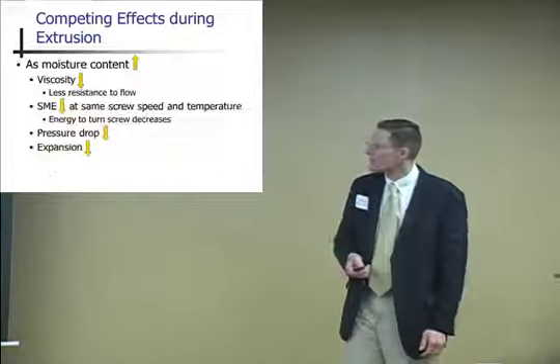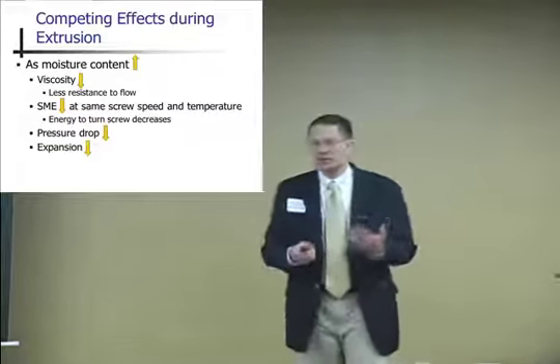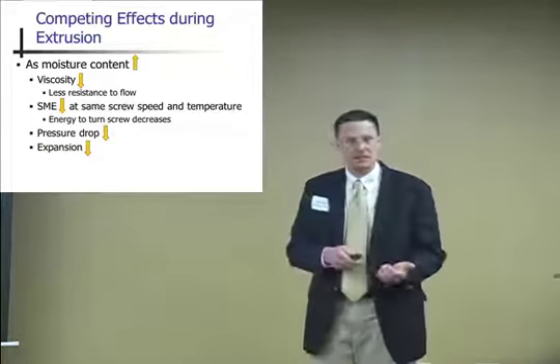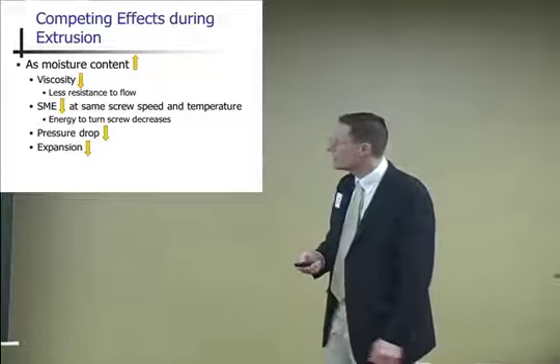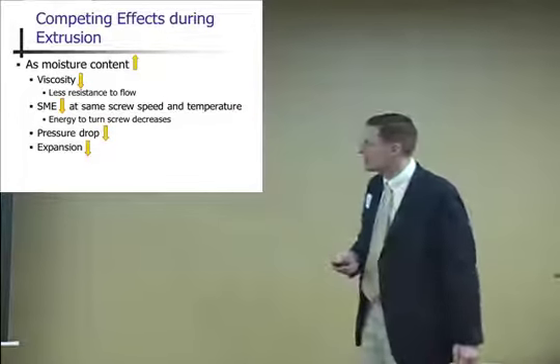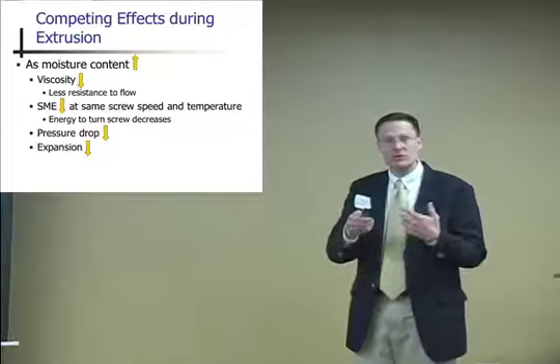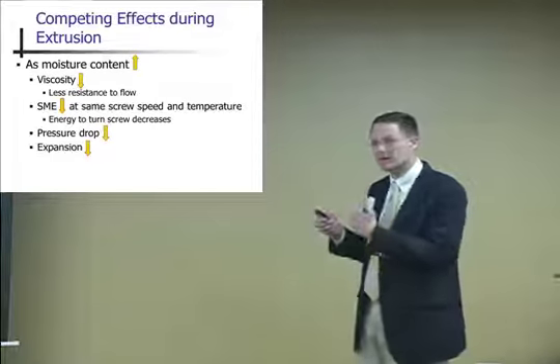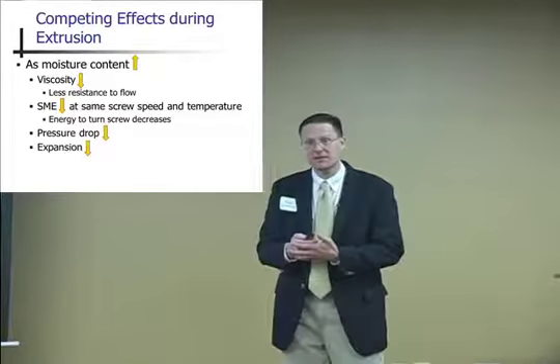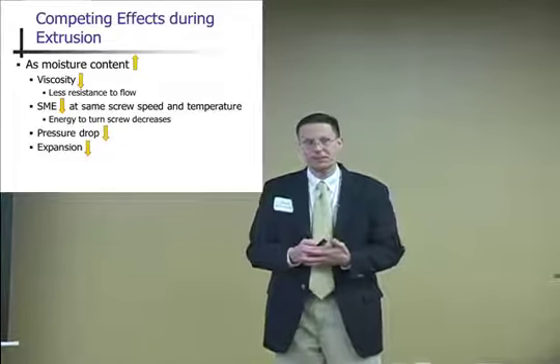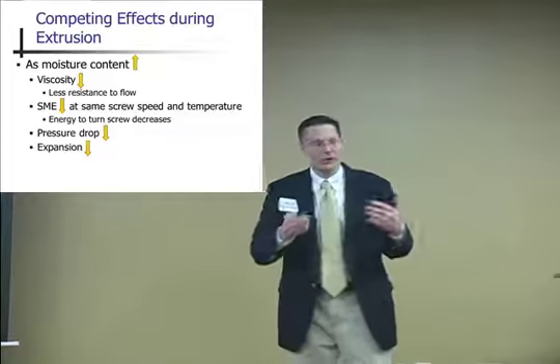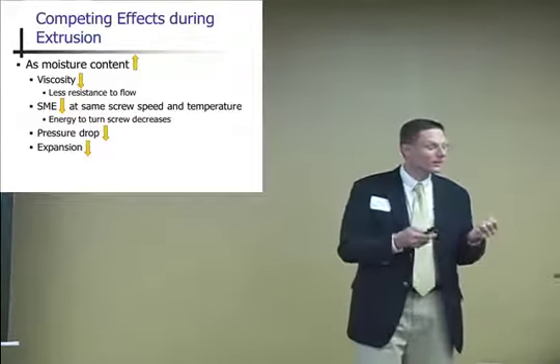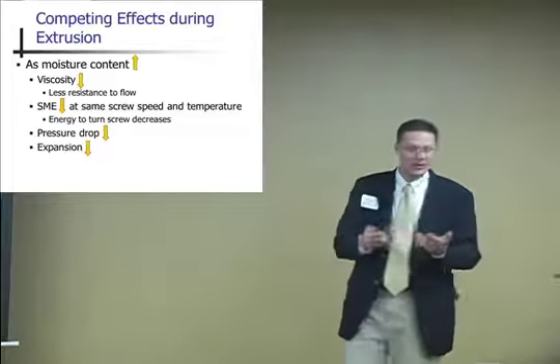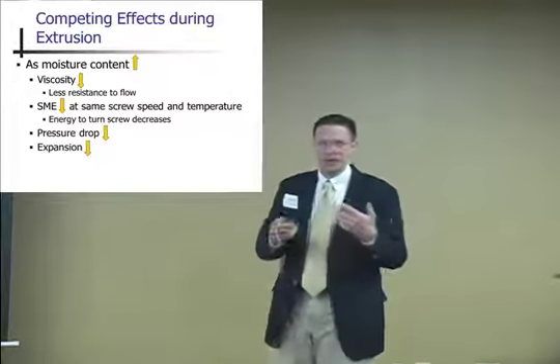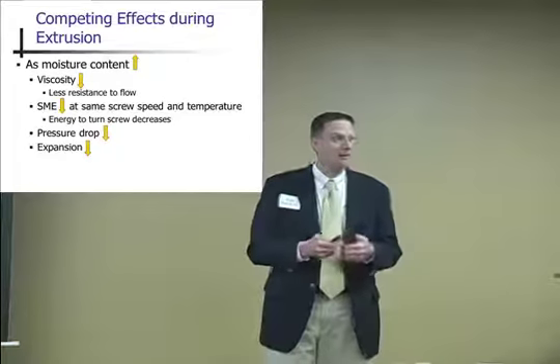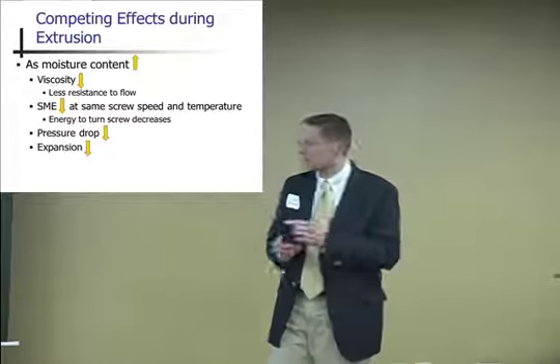Keeping everything else constant, as you increase your moisture content, your viscosity is going to decrease, which is good. Your SME is going to decrease because that viscosity goes down. Your pressure drop is going to go down, and theoretically your expansion is going to decrease too. So it's a trade-off. But your cohesion, your water stability, is going to increase. So if you're having trouble producing a pellet that's stable in water, increase your moisture content. That's the first thing I would tell you to do.